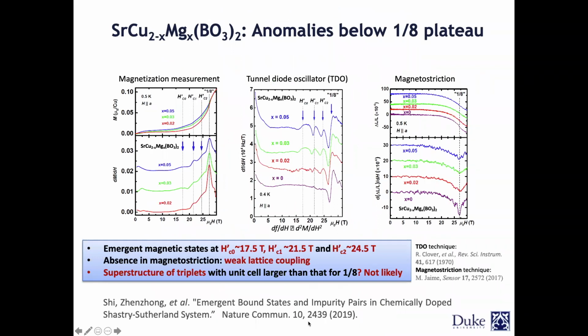Now, what did we do? We started to go to very high fields to see what happens. But not only in a pure compound: we started to actually punch a hole in these copper dimers, practically breaking them. That hole was nothing but magnesium, which is non-magnetic. So with the magnesium, we started to dope this system: strontium, copper, magnesium, boron oxide, with magnesium sitting in place of some copper.